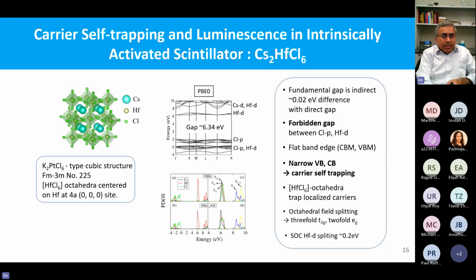You see these HfCl6 octahedra right there, hafnium at the center and chlorine at the corners. Although the picture looks like this, you have to pay attention: these octahedra are not connected to each other. In a normal perovskite halide, the octahedra would be connected through their corners or edges. But in this particular structure, the octahedra are isolated, meaning they're not connected through their corners, sides, or faces. Obviously, it's a crystal, so they are all bonded together. The bond is through the intervening cesium.